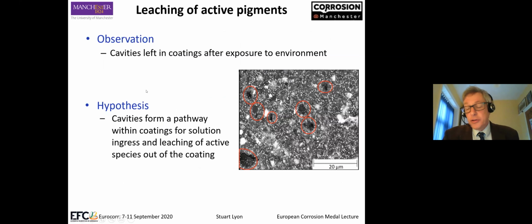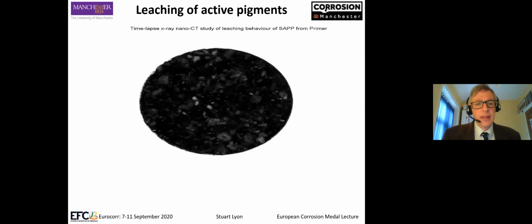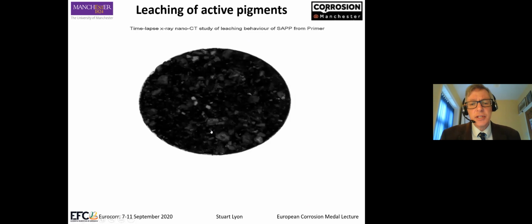Because a homogeneous polymer does not a paint make, paint contains pigments. So we observe that in many cases, cavities are left in coatings after exposure to the environment. And we could postulate that these cavities form a pathway for solution ingress and for leaching of active species out of the coating. And if that's true, we can then start designing coatings from more of a mechanistic perspective than from a formulation best guess perspective. And we did this work using a time-lapse video.